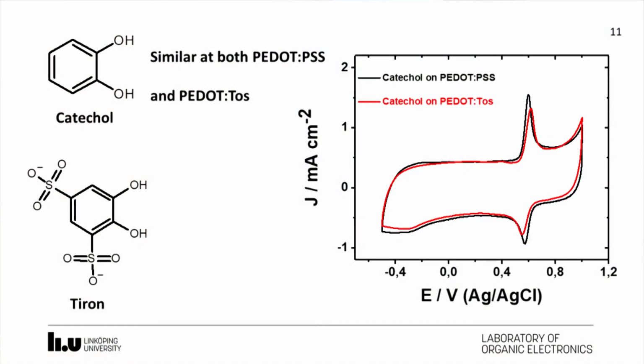In paper 3, we take two model molecules. The first one is catechol. The other one is tiron. Catechol is electrically neutral when dissolved in acid electrolyte, while tiron carries two negative charges due to this group. We found that for catechol, it presents similar peak current on both electrodes, with slightly higher current at the PEDOT:PSS electrode due to the efficient proton transport, as we discussed in paper 1.